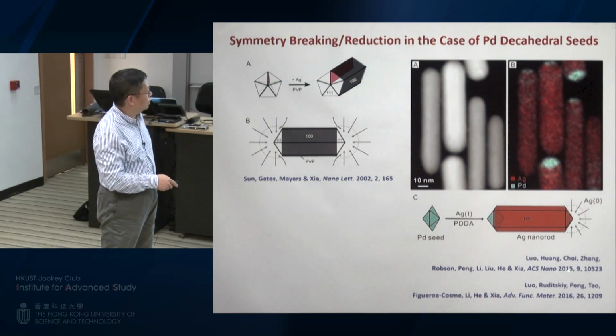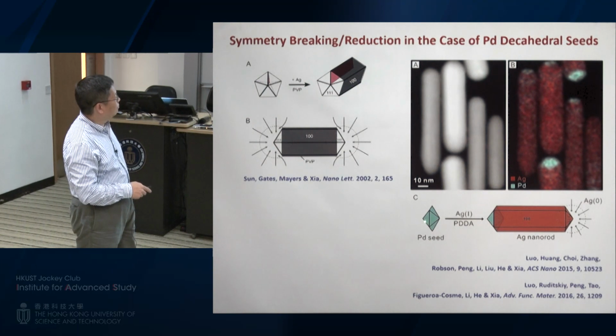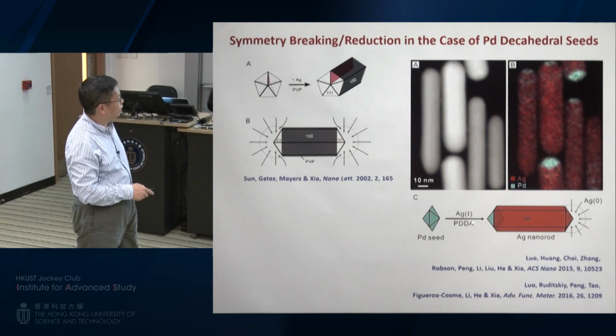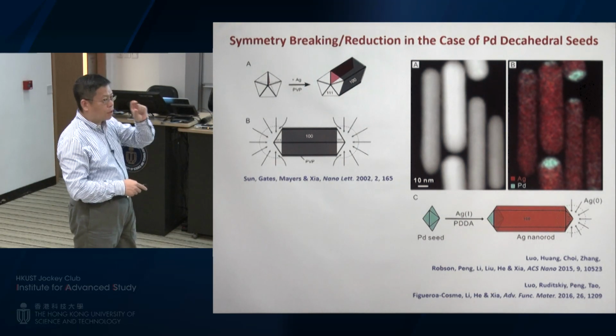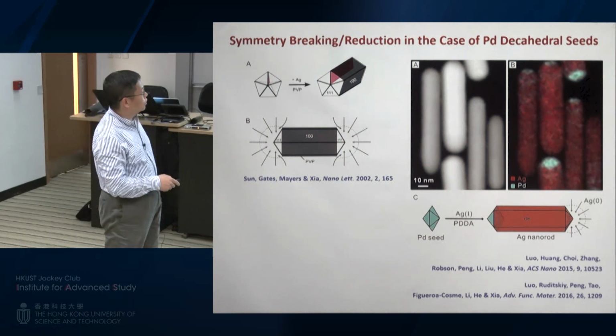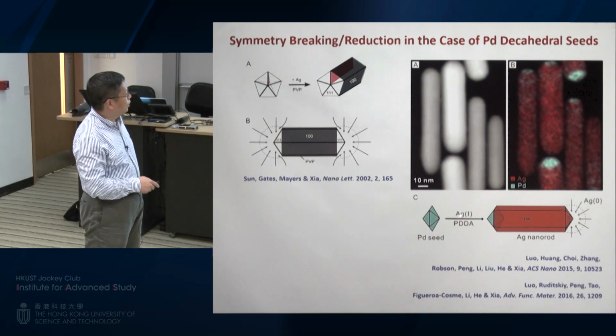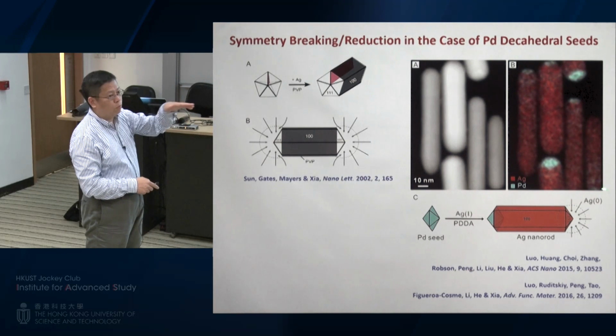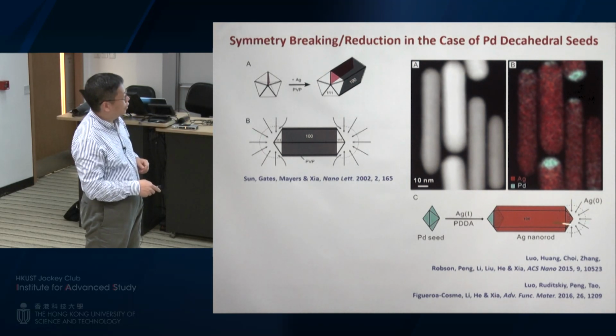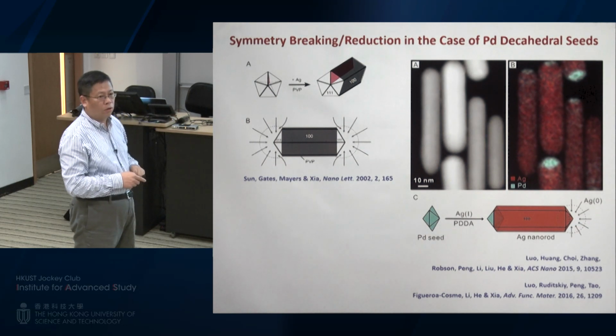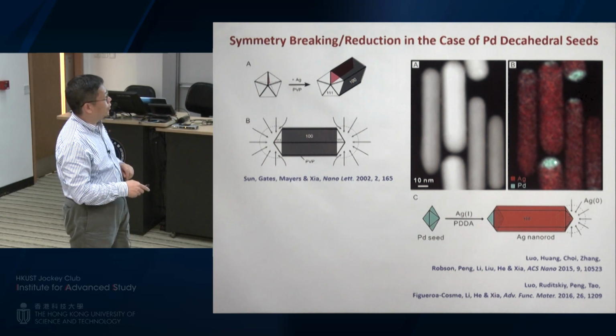For example, this is something we published 2 years ago. If you took a palladium decahedral seed, and you add this silver precursor and some reducing agent, under the influence of this polymer that can coordinate with silver ions and make the reduction slower, you can observe unsymmetrical growth. Basically, the growth will only be initiated from one of the two sides, not both sides, and eventually will push toward one direction. So that's why the silver will be deposited over here, and this end is still going to be covered by palladium. If you do elemental mapping, you're going to see it. Palladium is going to be located at one of the ends. So it's an unsymmetrical growth process.